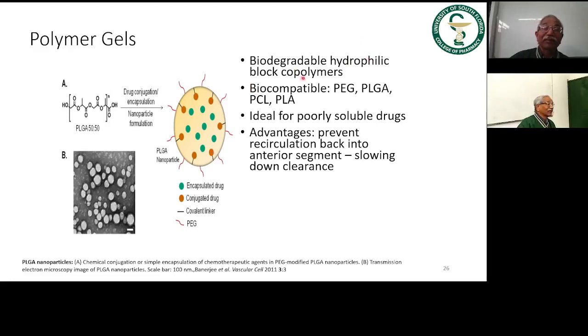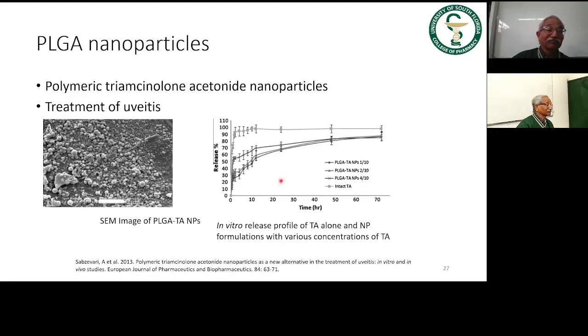So biodegradable hydrophilic co-block co-polymers are biocompatible, such as PEG, PLGA, PCL, PLA, ideal for poorly soluble drugs, prevent recirculation back into the anterior segment and slow down clearance. So that is the advantage of that. So this is the typical triamcinolone acetonide nanoparticle. Triamcinolone is used for treating macular degeneration. It reduces the macular degeneration. And this is how the sustained release is obtained.